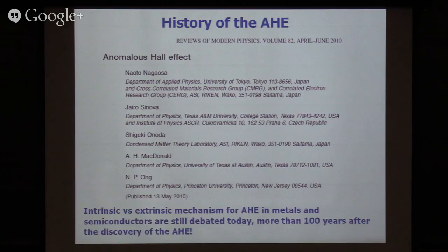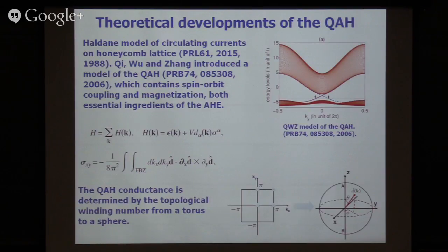So that leads us to another interesting branch of condensed matter physics called anomalous Hall effect. When Hall first discovered the Hall effect under magnetic fields, 10 years later he also discovered the anomalous Hall effect, due to magnetization in a ferromagnetic material rather than due to an external magnetic field. Now if we imagine a magnetic insulator, it can have a conduction band and a valence band. And very early on, Duncan Haldane constructed a honeycomb lattice model with a conduction band and valence band, but this time with only one chiral branch connecting the conduction band with the valence band. And one chiral branch is allowed because in this case, there's no time reversal symmetry.